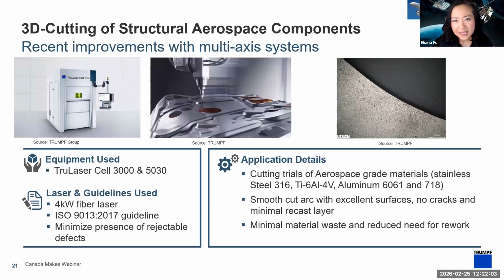And then some interesting parallel tests that we did in our lab in Michigan in the US, also using a different kind of machine, TruLaser Cell 3000, TruLaser Cell 5030, which are the small to medium sized machines. These machines are also used a lot in automotive cutting, but we extended that know-how to cut typical aerospace grade materials. So 316 stainless steel, Ti 64, 6061 aluminium, and 718 nickel alloy. We used a 4 kilowatt fiber laser for maximum power. We used this ISO standard, which I've put in the notes here, as a guideline, and tried to look for the minimum presence of rejectable defects according to that guideline.